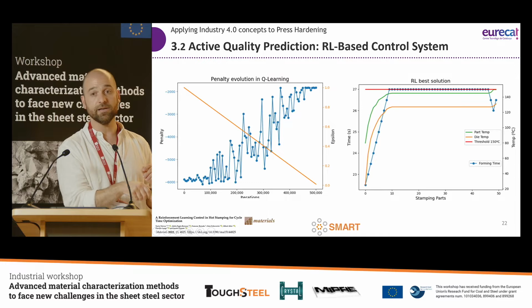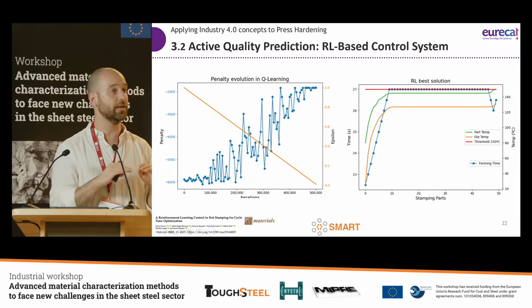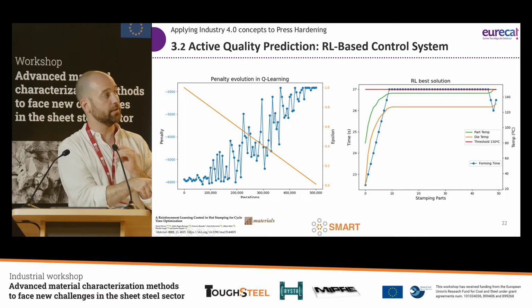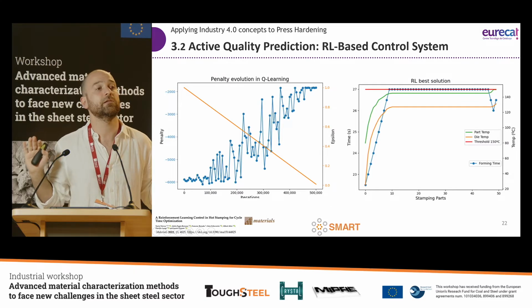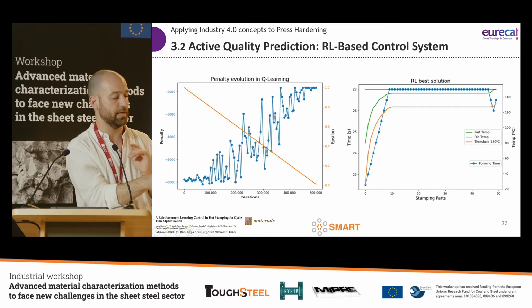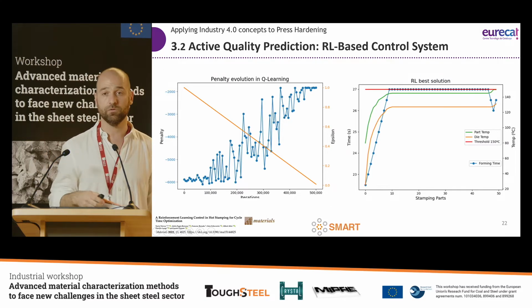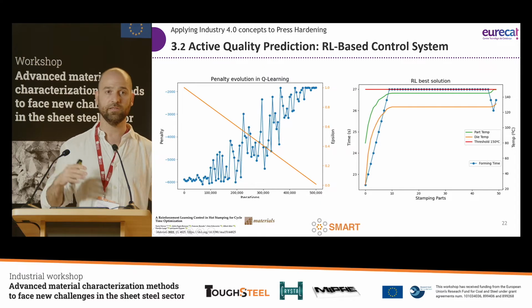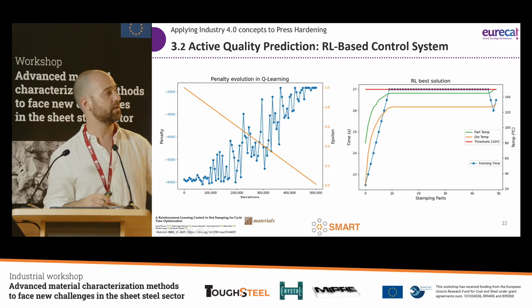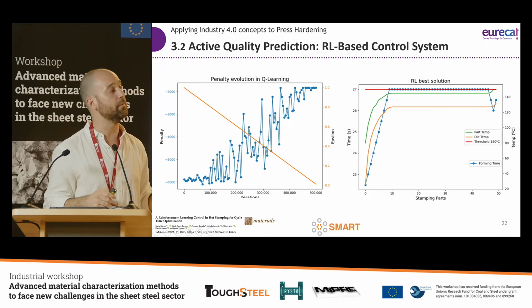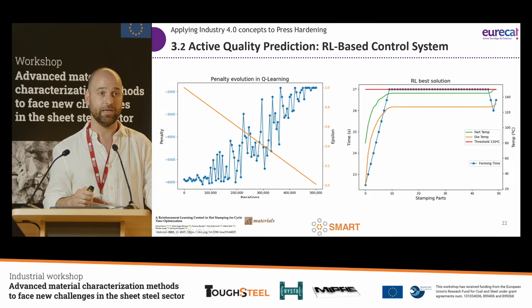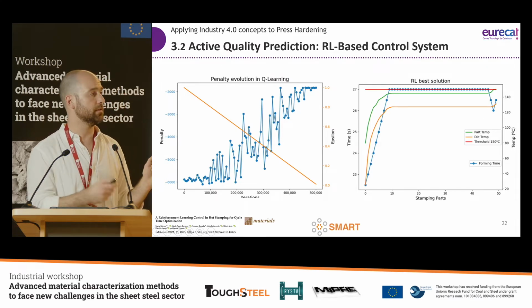So for the first cycle, it kept the die closed for a short time. The dies were accumulating heat. And once the dies were too hot, it said, OK, let's make it a little bit longer, and let's stay within this time. And this is more or less what humans do when we take simulations and we say, OK, in this line, we will put 25 seconds or 18 seconds cycle time. But this is being done by a machine completely autonomously. This is interesting, and this is a powerful result.